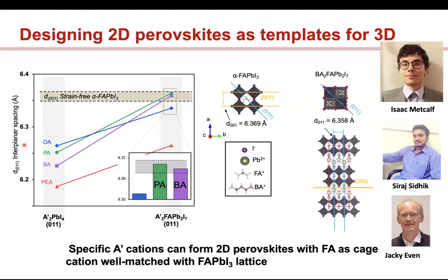So what I'm showing you here is the lattice parameter, essentially the interplanar distance of the 0, 1, 1 plane, right? This is my FAPI. This is the bulk 3D FAPI. And on the bottom x-axis is the lattice parameter of the 2D perovskites, right? So this is N1, right? You can see that these lattice parameters are very far from this 3D. But if I go to an N2, right, if I make a 2D perovskite where I have FA as a cage cation, right, not methylammonium, but FA, then I can make a 2D perovskite which has the same lattice constant or very close to that of my 3D perovskite. Okay.